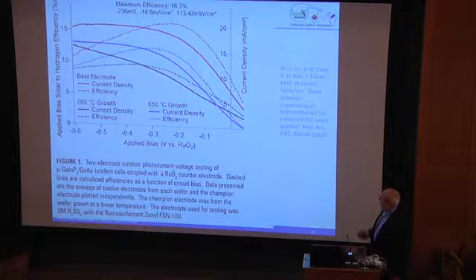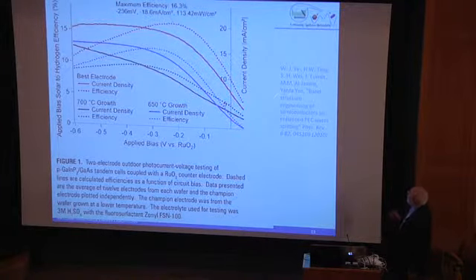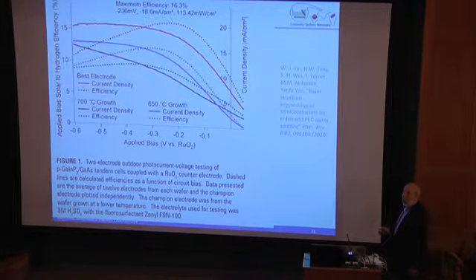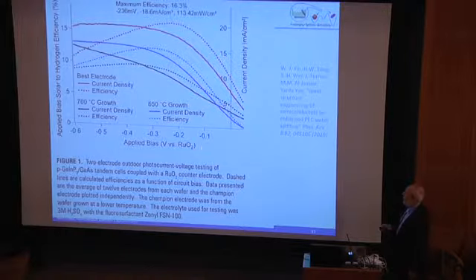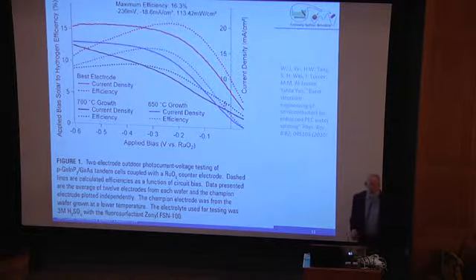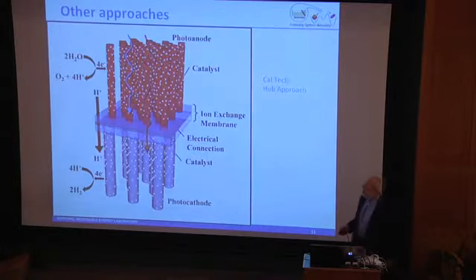So what does this show you? This is the idea that you can put a catalyst on the surface, and I think this is actually meaningful. This is high temperature growth of the material and then water splitting using a ruthenium-based catalyst. And I think what it says is that catalysis can make a big difference. We don't know what the right catalysts are right now, nor do we have a good model for how to do this. The very first use of ruthenium oxide on the surface was Adam Heller at Bell Labs, again, a very long time ago, and I don't think we've substantially improved on this.